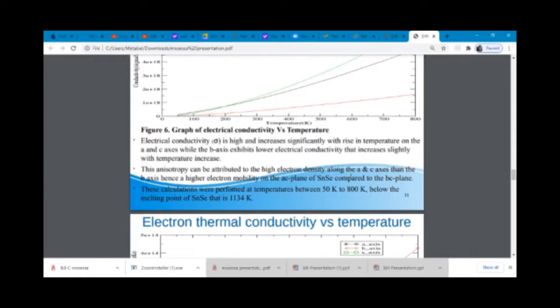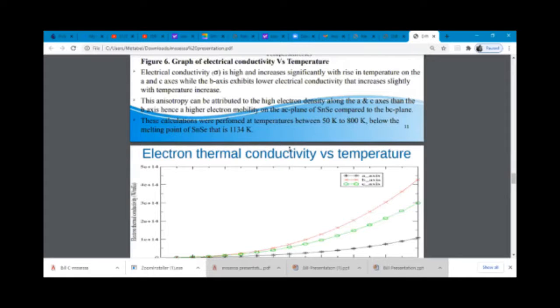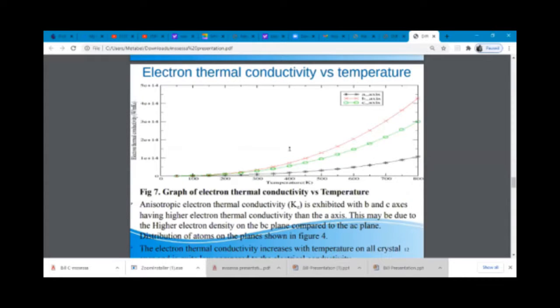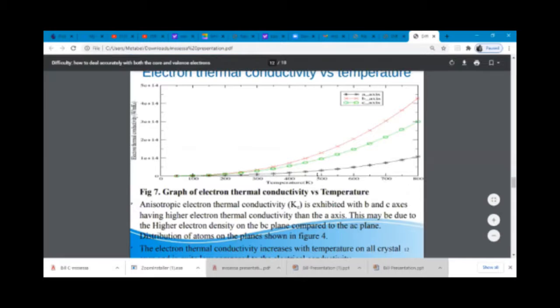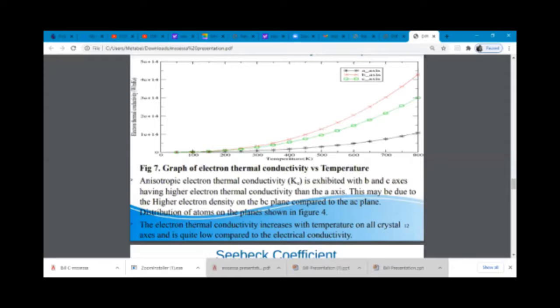The next one is the electron thermal conductivity versus temperature, how the electron conductivity behaves as the temperature increases. It's the same as the electrical conductivity, but the values of the electron thermal conductivity are quite low as compared to the electrical conductivity. The electron thermal conductivity was also found to be anisotropic in that the B and C axis demonstrated a higher electron thermal conductivity than the A axis. So this anisotropy may be attributed to the fact that the BC plane has a higher electron density than the AC plane.